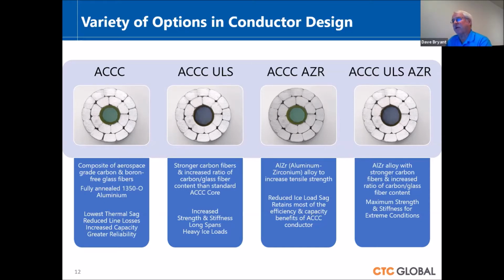through those wires. Also to mitigate extreme ice load conditions or the 2-mile river spans, we've developed the AZR, which is essentially just a plain ACCC or a ULS core that has aluminum zirconium alloy to give the conductor additional strength. We normally use fully annealed aluminum. It has an IACS rating of 63% of annealed copper. The AZR drops it down to about 60%, but you get a lot more strength and only give up a little bit of the efficiency aspect.